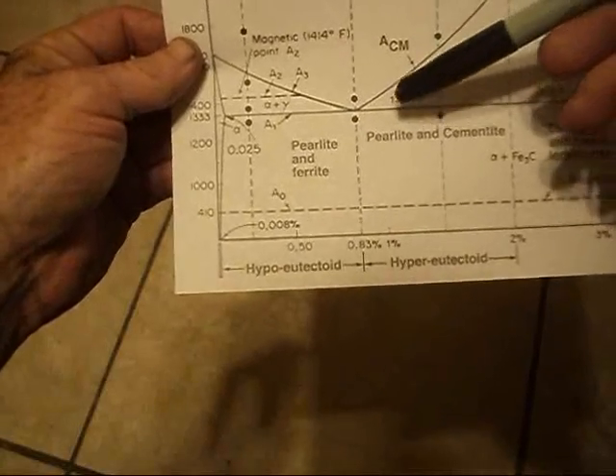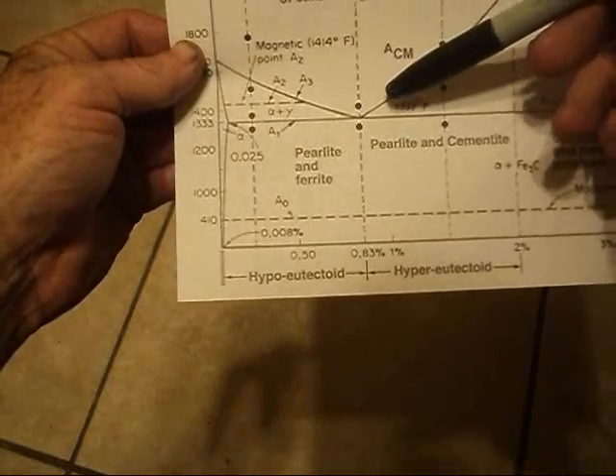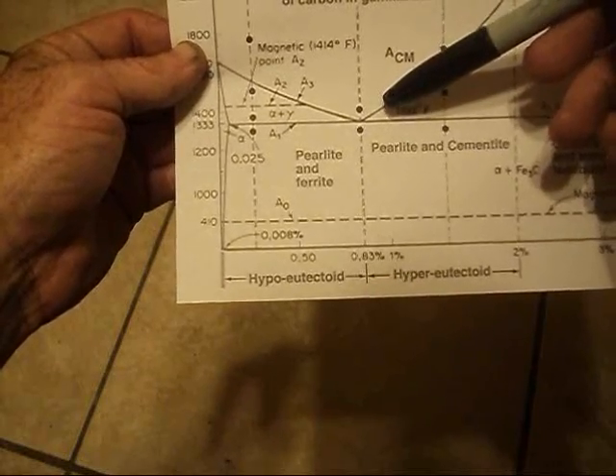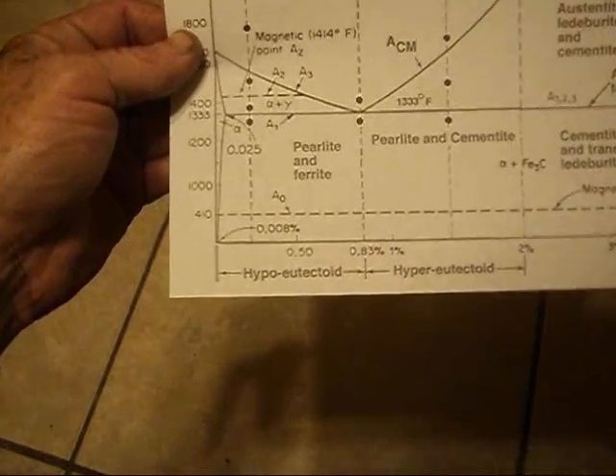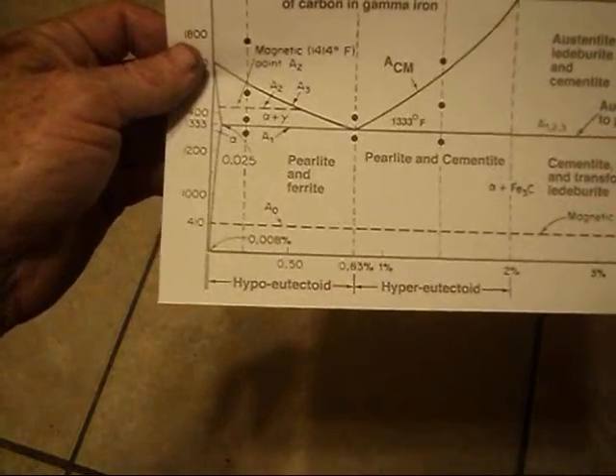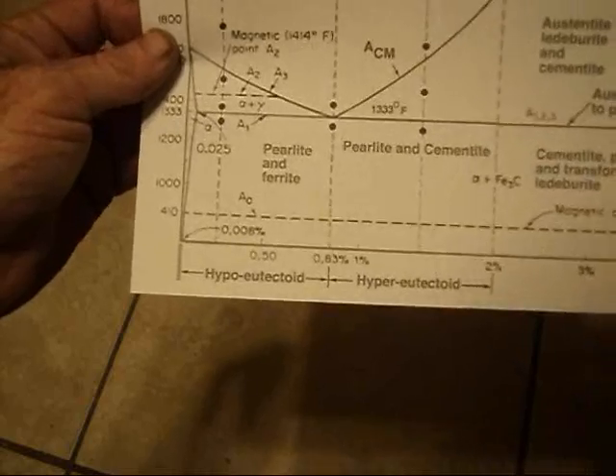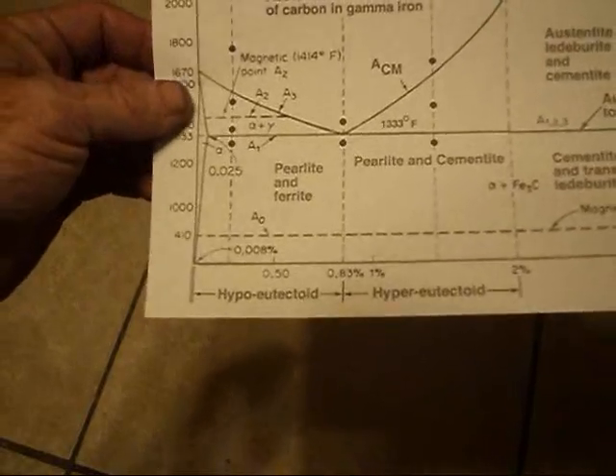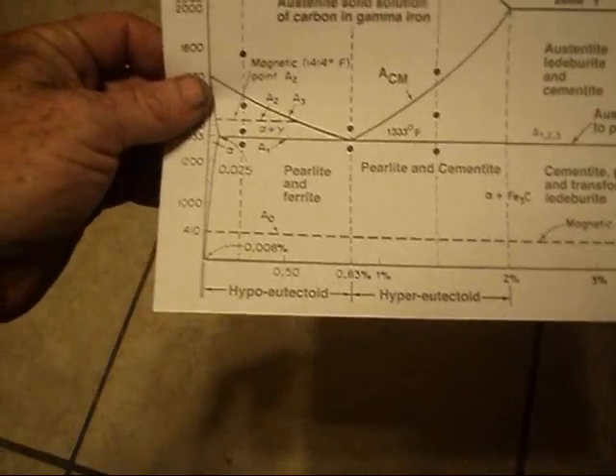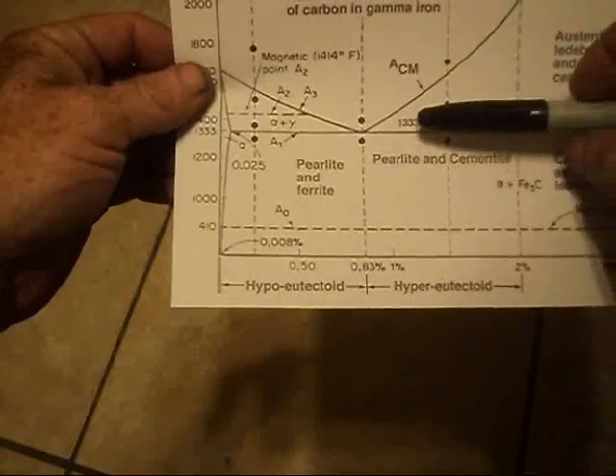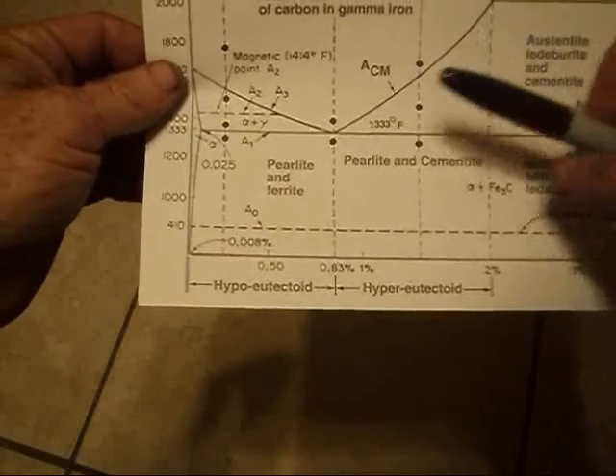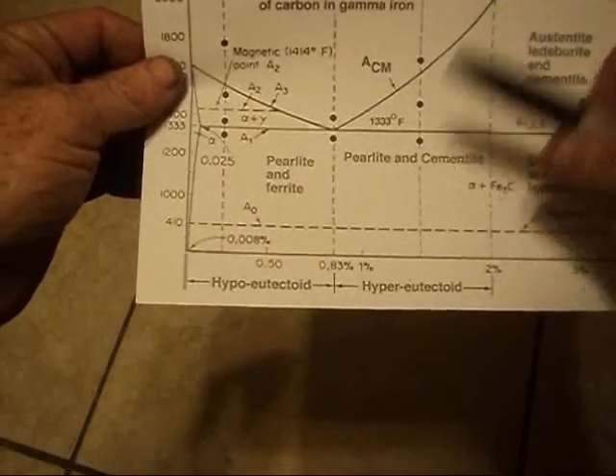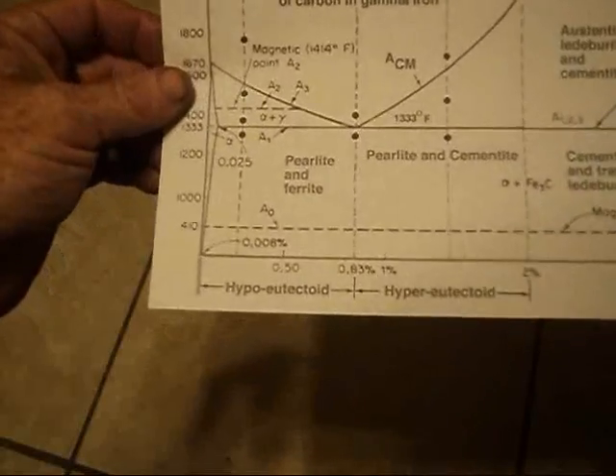But it looks like the upper transformation line is right about probably 1425. I've always heat treated 1095 at about 1450, 1475 to be honest with you. If you don't have a pyrometer and you're using a magnet, just when you find out that it won't stick to a magnet, just heat it just a little bit hotter. Not much at all. And then quench it.